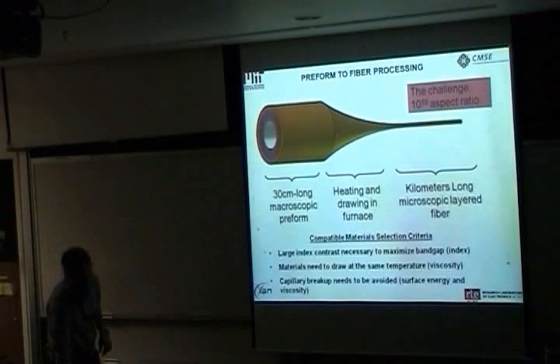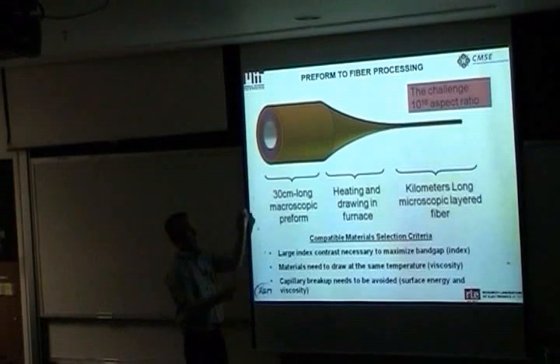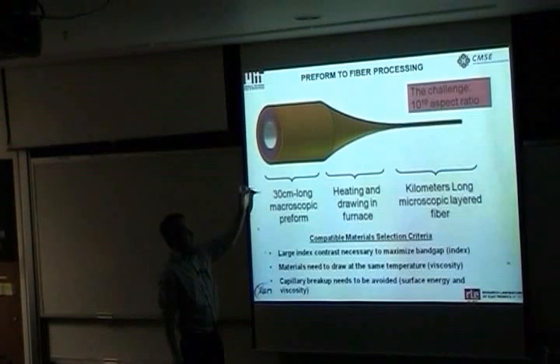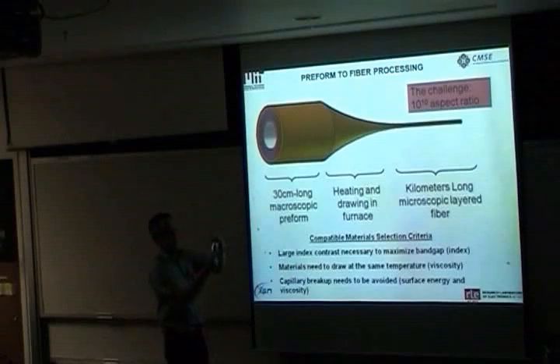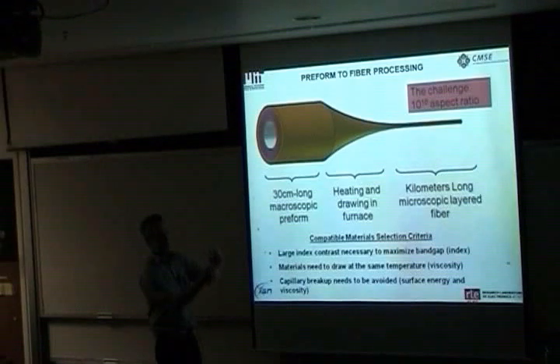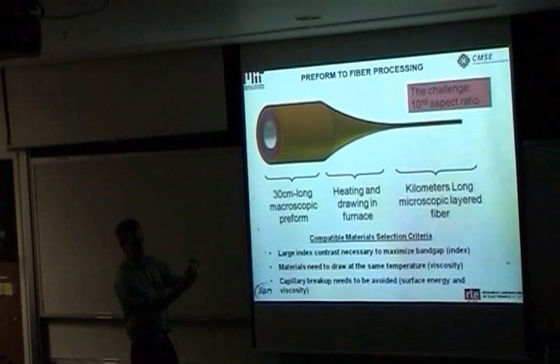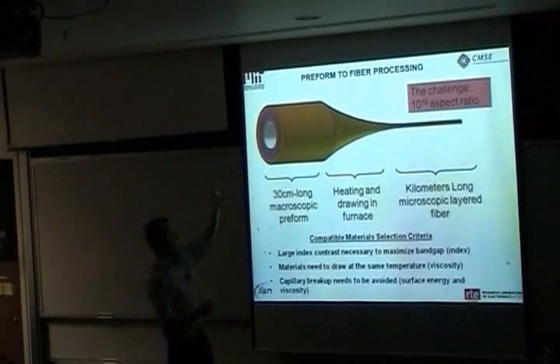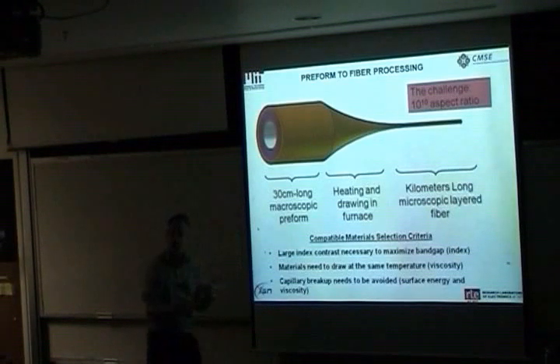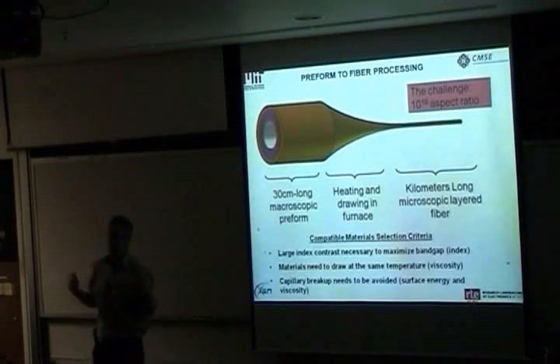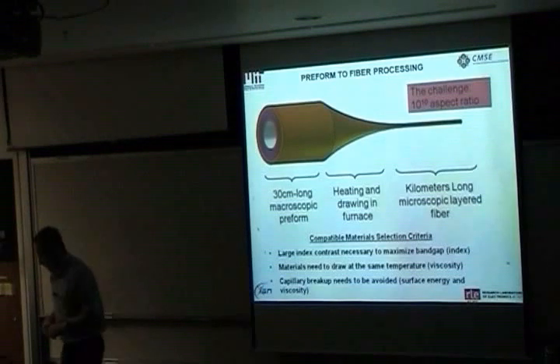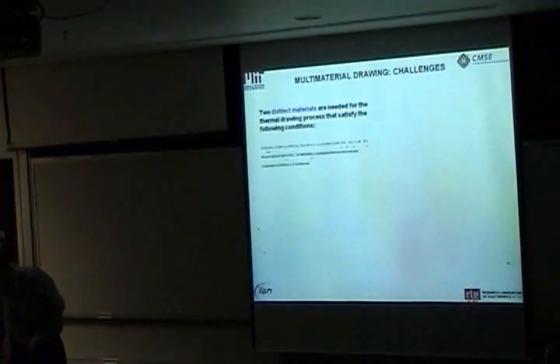And what we did was look at how silica fibers were made and realized that what's really beautiful about the process of making fibers is you start off with the preform. It's a large object. It is exactly a scaled up model of the final fiber, so it has a hollow core, it has a cladding, and it could have the layers inside. And so what we imagined is building one of these preforms out of materials that all flowed at the same temperature. And the hope was, well, we take it, we heat it up, we draw it into a fiber, and that's it. And we don't have to worry about microfabrication, nanofabrication.